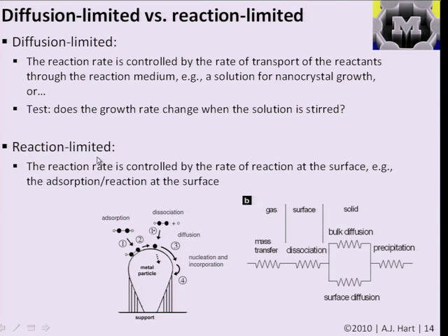We're supplying enough precursor no matter what rate the particle wants to grow at. But if we have a relatively low concentration of precursor, then it could be that we're going to be limited by diffusion. We're not providing enough concentration gradient between the surroundings and the particle to grow the particle at the rate that it wants to grow by the basic reaction.